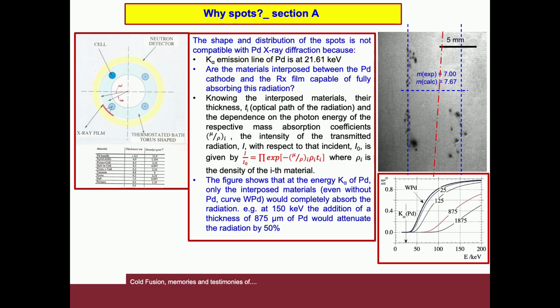The thickness corresponds to the optical path of the radiation. It's necessary to know the dependence on the photon energy of the respective mass absorption coefficients. The intensity of the transmitted radiation I, with respect to the incident I0, is given by this relation written in red, where ρi is the density of the ith material.